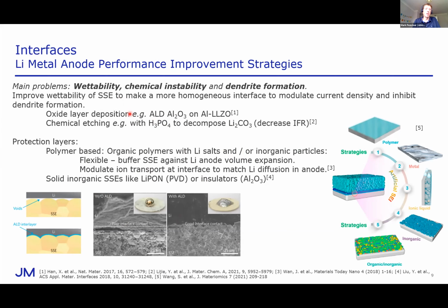Loads of potential ways of doing that. One of which I've just highlighted here, which is the atomic layer deposition of alumina onto this garnet material. And the TEM from the literature shows that in the absence of the coating, you get this delamination, which is going to lead to inhomogeneous contact and different current densities. And you can see that the photograph shows the effect. The wetting is very poor. In the presence of the coating, the interface is much better, much more homogeneous, and so the wetting is improved, and that's advantageous.